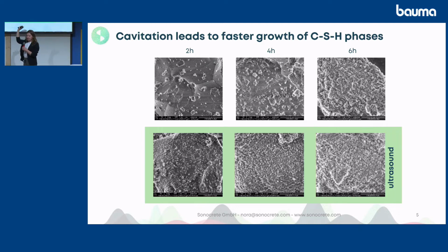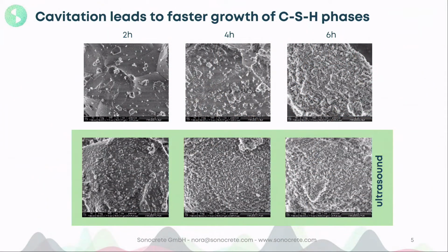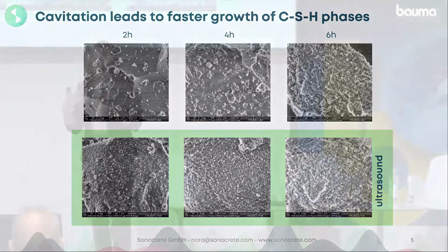Showing you this from the scanning electron microscope, on the top you see an unsonicated sample of concrete. The CSH phases you cannot really see in the first picture. There are only a few very small white blocks. They are growing after 4 hours, and there are a lot of them after 6 hours. But if you look at the sonicated sample, after 2 hours you can already see, I hope you can see it, a lot of those little white blocks, and they are very evenly distributed. So everywhere CSH phases are starting to grow. With them being everywhere, when they start to grow, they can interlock very quickly. That's what you see after the 4 hours, and after the 6 hours it's practically done. So this is what happens on the chemical side.